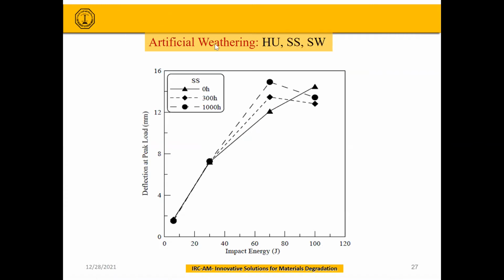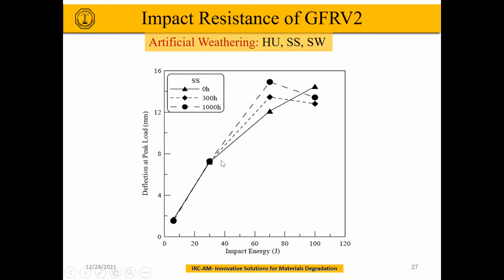The impact resistance of the material, also you can see that for the deflection at peak up to impact energy of 20, there is no effect of the exposure to humidity, salt spray, and seawater. As you increase the impact energy, it shows that humidity and salt water affect the deflection at the peak load.